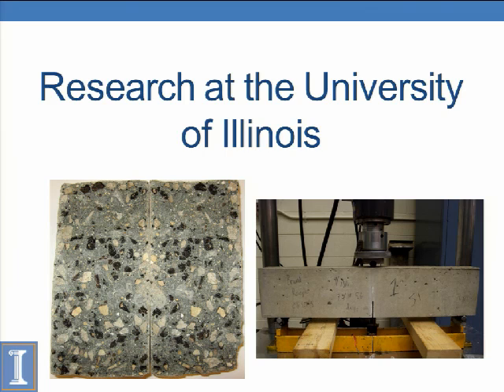And you can see, here's your virgin aggregate, and it's cracked right through. Here's one of the FRAP particles you can see on either side with a very thin asphalt coating. Those particles fracture through. But if you look at some of these, what I'm thinking are either agglomerated particles of sand and asphalt, or there's actually an aggregate in there, and that's just the film that cracked through. So it really does look like there is a bond issue here. And that is something that I'll be looking into for my PhD, seeing if we can do anything to help this bond issue and improve this bond.